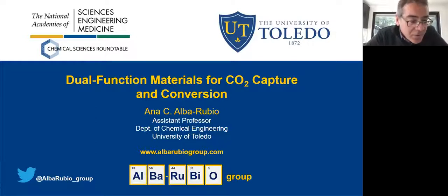So the degradation mechanisms for amine solutions and solids, that's always an issue that you need to address. And the current materials being used do degrade fairly quickly. And so the way we're tying down the amines in these solids can actually lead to longer lifetimes, where the decomposition pathways accessible in solution are not necessarily accessible in these materials. Also, if you operate at lower temperature conditions, you have less degradation. And so one of the advantages for these materials can be less degradation as you cycle.